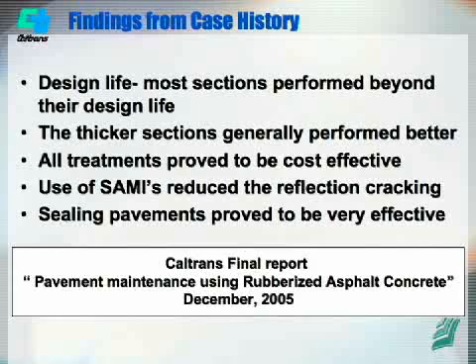Basically, the sections that had SAMI had less cracking. So the SAMI with the pavement preservation strategy is an excellent strategy, utilizing an interlayer below that thin layer. The other finding, of course, was the thicker the better. If we use 30 millimeters, it's much better than using 19 millimeters. So thickness is very important for reflective cracking. Also using SAMIs is very important.